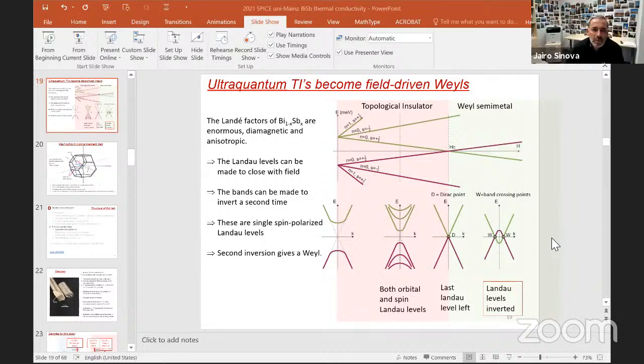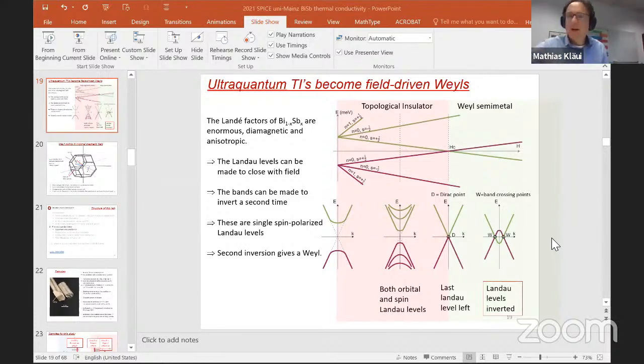Matthias, you're going to mute yourself and ask the question. Thanks for this really nice talk. I have a question concerning the importance of the charge carrier density. So you mentioned that you have very low charge carrier density in your samples, like 10 to the 15 per cubic centimeter or something like that. So maybe you can comment a little bit where the residual charge carriers come from. Or for instance, do the bad samples have much higher charge carrier densities?